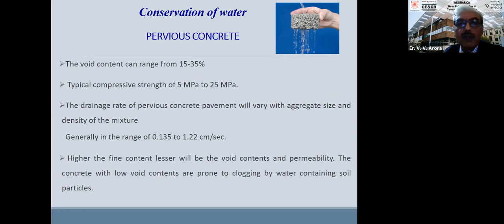The void content ranges from 15 to 35% and strength is 5 to 25 MPa. ACI has a good specification on this pervious concrete, and ISO is making a specification on pervious concrete. The test method on pervious concrete has also already been made by ISO. The drainage rate is generally in the range of 0.135 to 1.22 centimeter per second. Higher the fine content, lesser will be the void content and lesser will be the permeability.